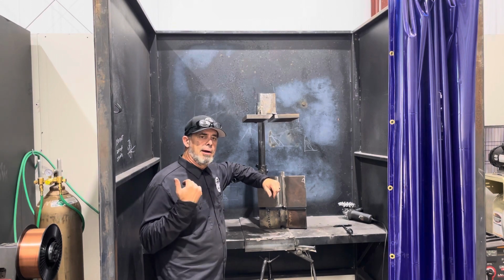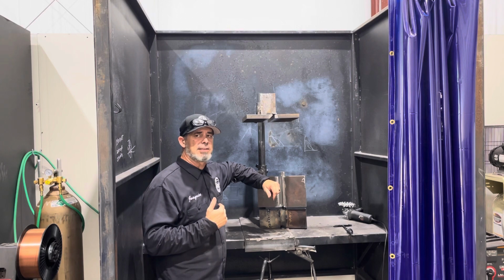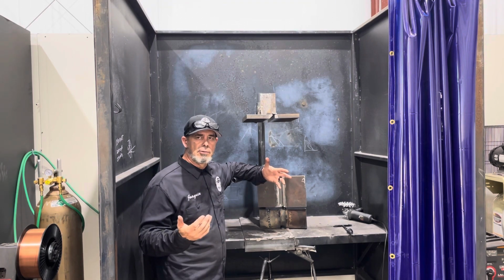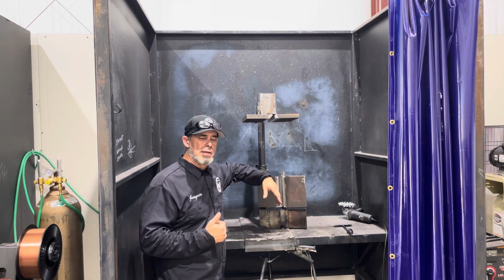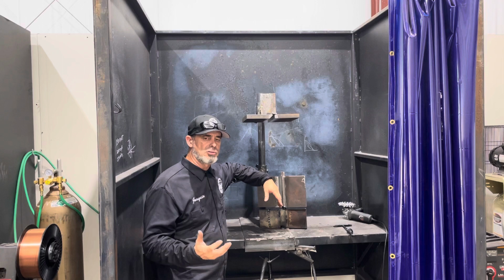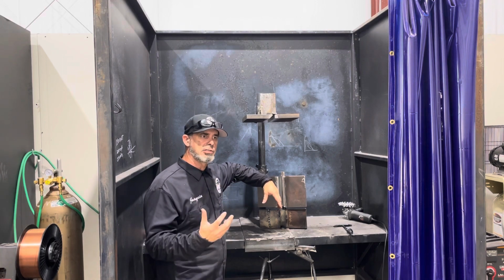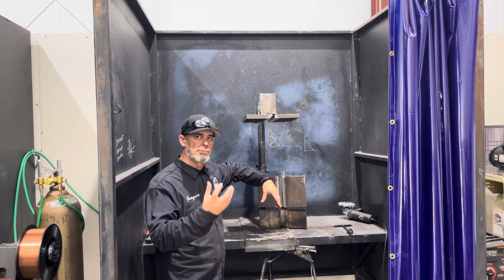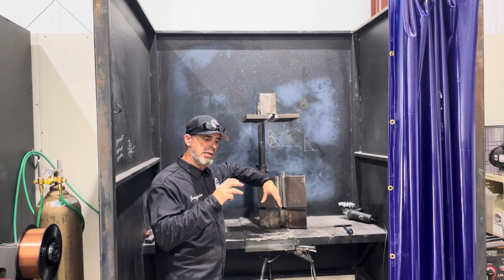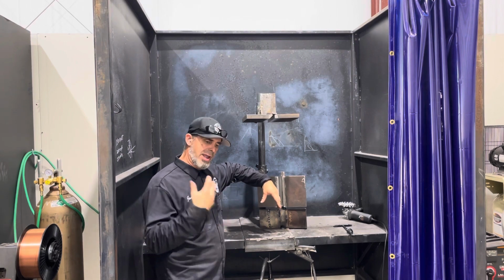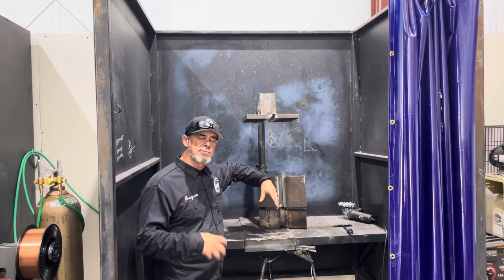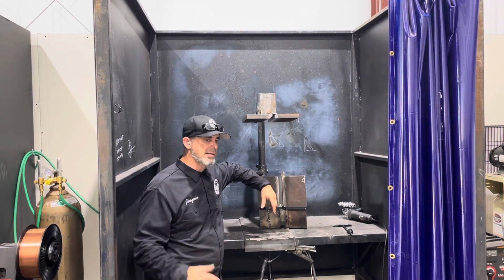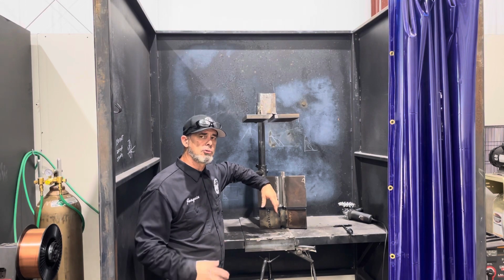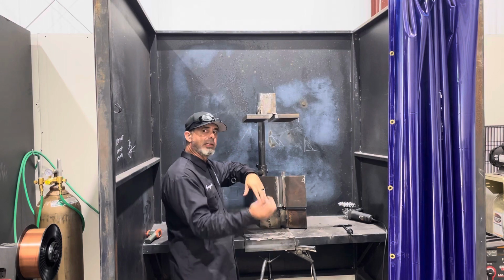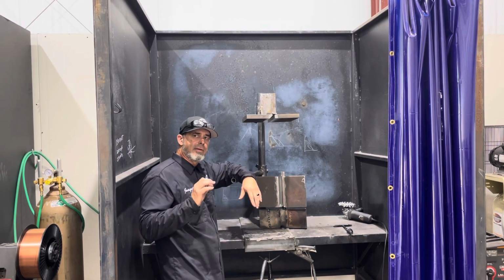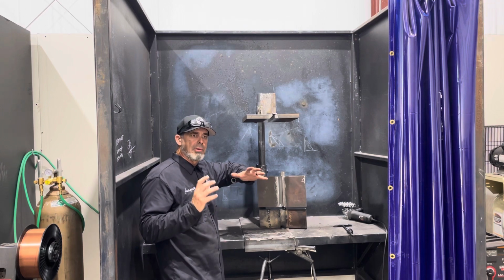So again, with this material, because it is 50,000 PSI higher than A36, when you're dealing with A36, it is a lower tensile strength, and I don't want that to be on the surface of my material if that were to happen. When you grind material, a lot of times that material will actually bond to whatever you're grinding with. So it'll actually be in the pores of your grinding wheels. The grinding wheels do wear and that comes off, but there is a chance of actually grinding that onto your material. Why take that chance? Grab a new wheel. Make sure that you don't use that same wheel to grind something off the table and then touch your coupons to it. You're trying to create a very clean surface for your coupons to bond with the filler metal.